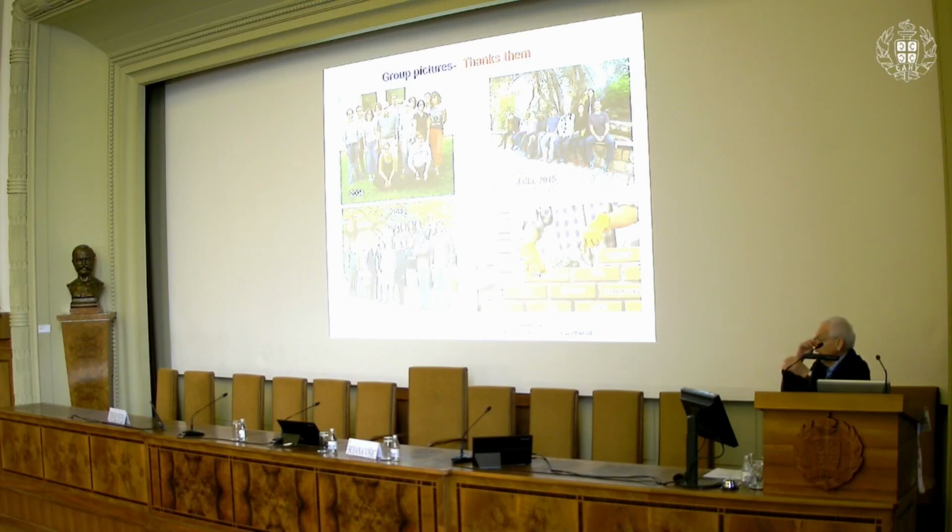His group made electrical gating using a liquid ionic gate, and they measured beautifully the superconducting of a single tungsten disulfide nanotube, and furthermore they showed the diameter dependence of the superconducting transition. Of course, this was electrical measurement, but not magnetic measurement.